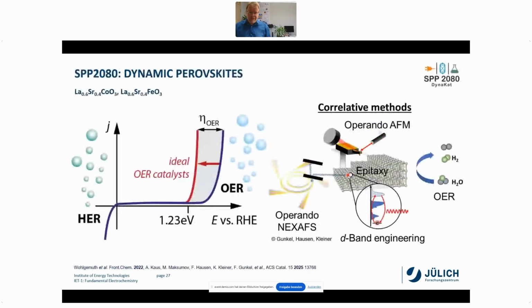Yeah, thank you, Ini. And Ini has shown you how we can measure with friction different states at the interface. And we use this to study perovskites. Perovskites are an interesting material. In this case, we use lanthanum strontium cobalt oxide and lanthanum strontium iron oxide, LSCO and LSFO, because we can use them for water splitting devices.